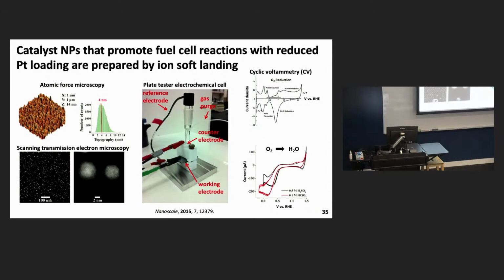So to test the catalytic activity, again, we can combine this into an electrochemical cell. Our surface basically goes here. There's a small volume of electrolyte trapped above it. We purge that alternatively with argon and oxygen, depending on whether we're making a background or a reduction measurement. And then we obtain the CV, and the critical value is the position of this voltage here, right, this curve. And we can make things that have comparable reduction potentials to precious metals, but contain a much lower loading of those metals.